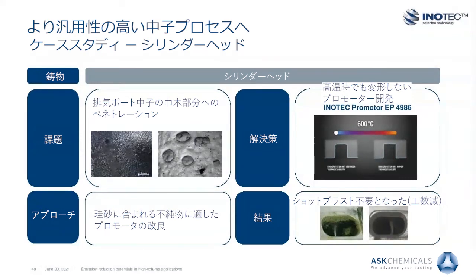A predominant problem area in the production process of cylinder heads using inorganic binder systems is the appearance of sand adhesions and penetrations after raw part machining, especially on the core print areas of the port cores. This defect is described by the partial appearance of sand grains on the casting surface due to the mechanical penetration of the liquid melt into the sand core surface or the electrostatic adhesion of sand grains on the casting surface itself. Casting parameters, for example casting temperature and pressure, have an influence, but customers are seeking a chemical binder solution that removes the need for intensive process control and casting rework by shot blasting.